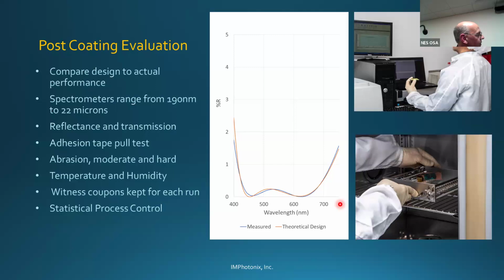Some of the other tests also mentioned in ISO 9211 are adhesion and abrasion. A typical test for adhesion is just a standard tape pull test, where you would apply tape, Scotch tape, to the witness sample and pull it, and then inspect it to make sure no film has come off. For abrasion, there are two types: cheesecloth for moderate abrasion and the eraser test for hard abrasion.